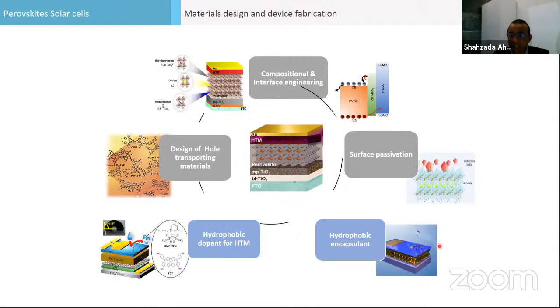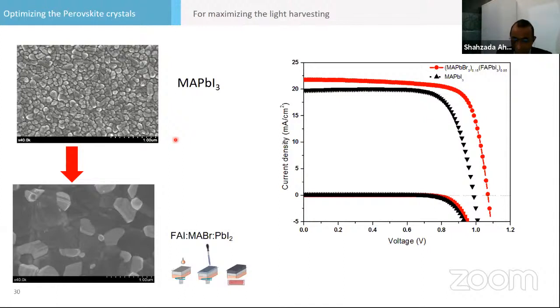I'm talking about ionic liquids. Ionic liquids, we know, are salts but liquid at room temperature, and they are very good to increase the stability because the surface tension is very high. And then hydrophobic dopant, the same way. And we also design a hole transporting material, p-type, which can do that. Just to give you a flavor of the research, why we do that.